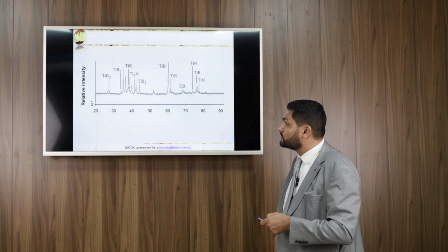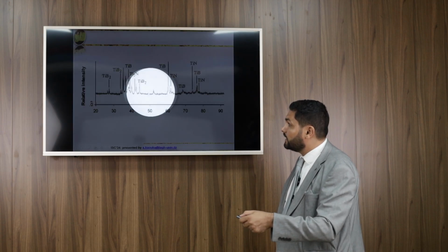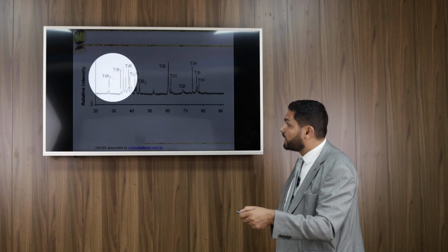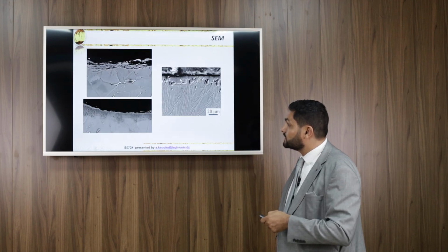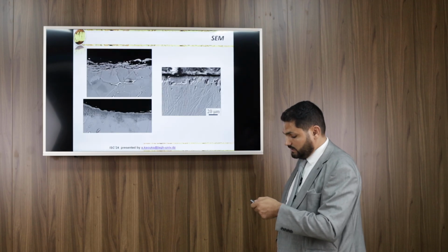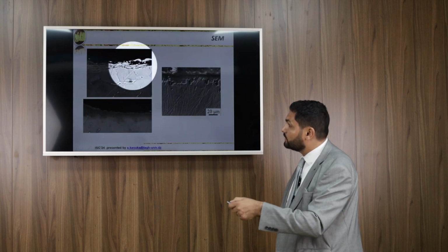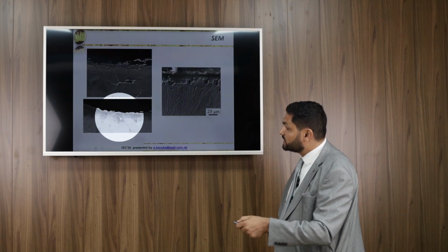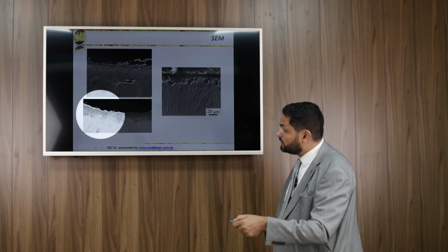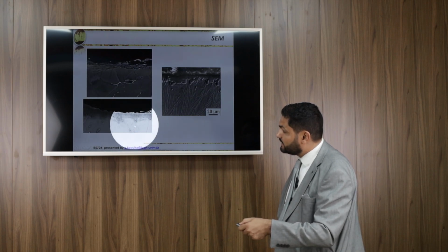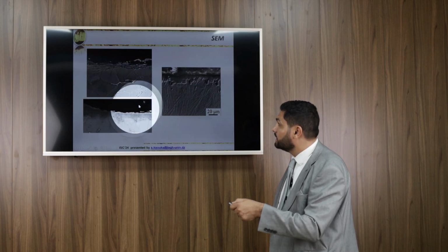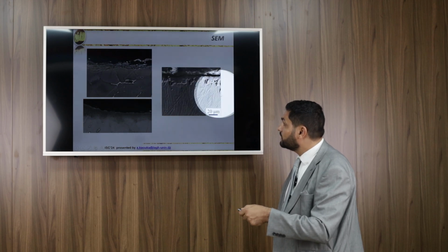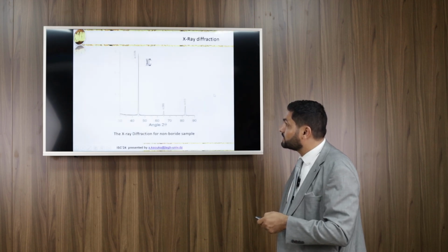This is the structure before treatment and this one after the treatment. We see the diffusion of the elements. This is the titanium diboride, and this is the laminar structure here. You can see the formation. This is the boride layers formed, and this is the substrate, as you see here.